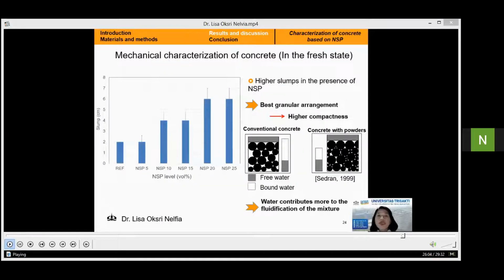The workability test shows that the presence of NSP in a concrete gives a higher consistency result than the conventional concrete, whatever the substitution rate is. According to recent research, the workability result at each substitution level is always higher than the reference material. It means that the nickel slag doesn't absorb water, low water absorption. This result is surprising considering the fineness of NSP particles, finer than cement. The material tends to affect the rheology of a concrete because it absorbs less water and increases the compactness of the granular skeleton because of its nature and shape.